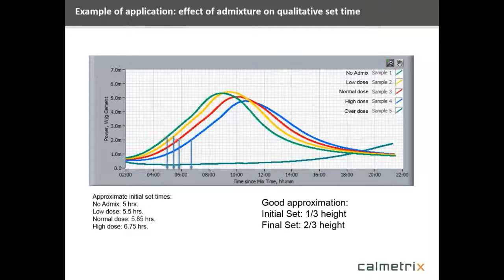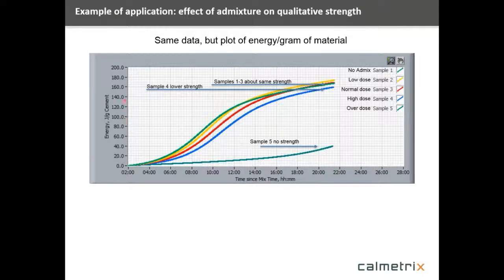So you can very quickly, graphically, look at the effect of the admixture on the set time for these four samples. Of course, you can see graphically here the sample that's been overdosed really, within the time frame we're talking about, does not go through any kind of set. The reaction has been almost completely damped out. Now, since this example was done on an isothermal instrument, we can also integrate under these curves. And when we do that, we look at this continuous energy curve in joules per gram as a function of time. So here we're looking at something different.